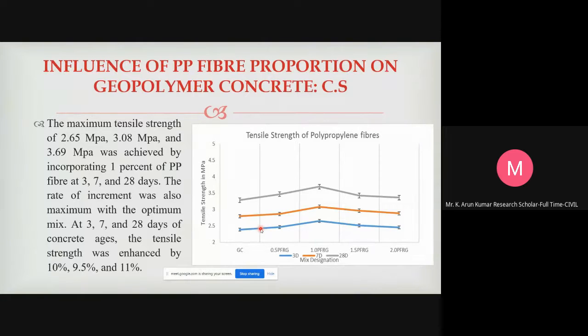Similar to compressive strength, the maximum tensile strength was observed with the 1% addition: 2.65 MPa at 3 days, 3.08 MPa at 7 days and 3.69 MPa at 28 days, where the strength increment percentages were 10%, 9.5% and 11% respectively.